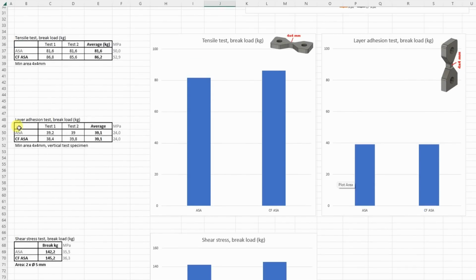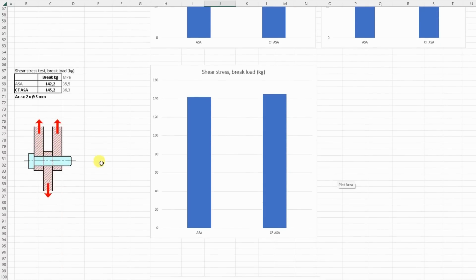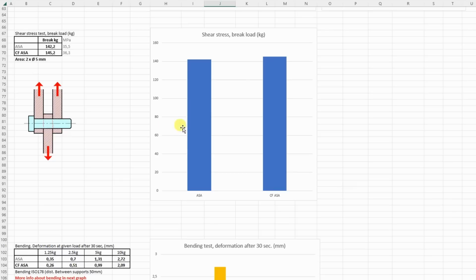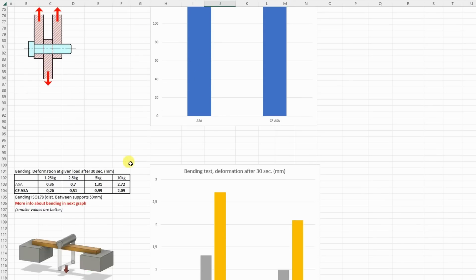The tensile and the layer adhesion test. The smallest cross-section area of these objects is 4 by 4 millimeters, printed horizontally or vertically, and I got very similar values with these two filaments. And this is very good layer adhesion too. Almost 40 kilograms for the breaking on this size. The shear stress, again, good results and very similar in both cases.